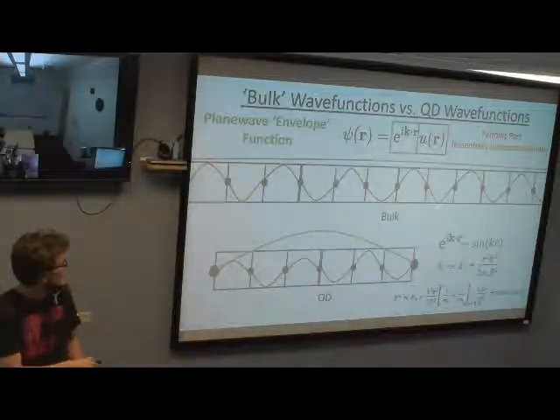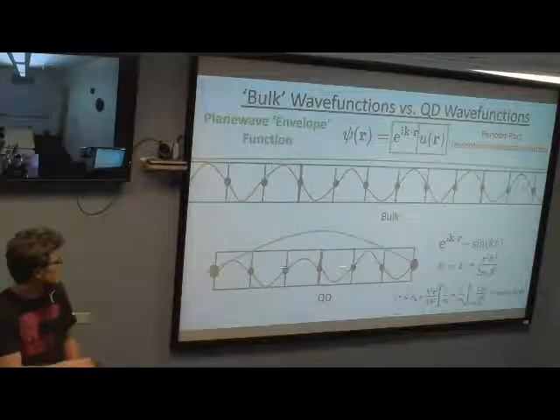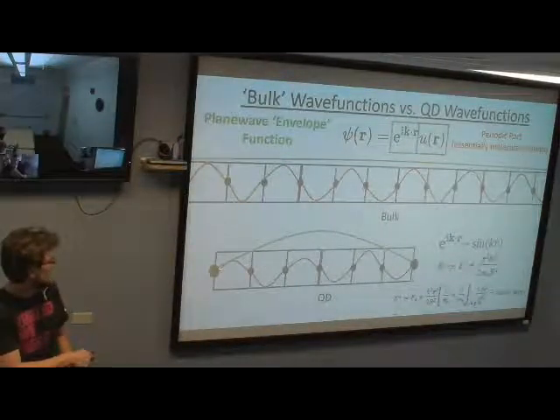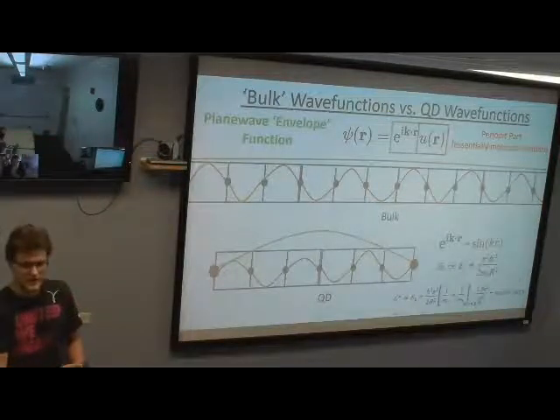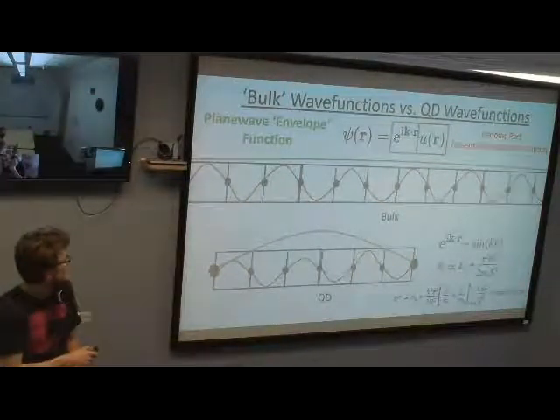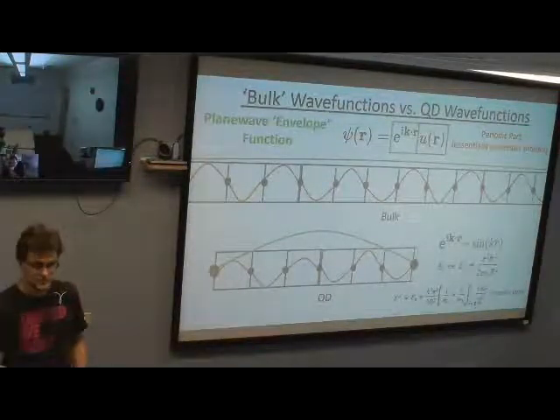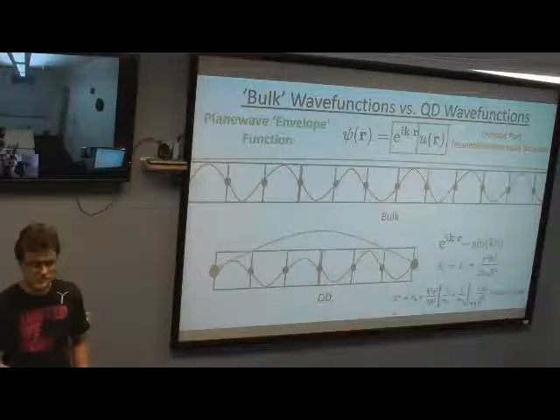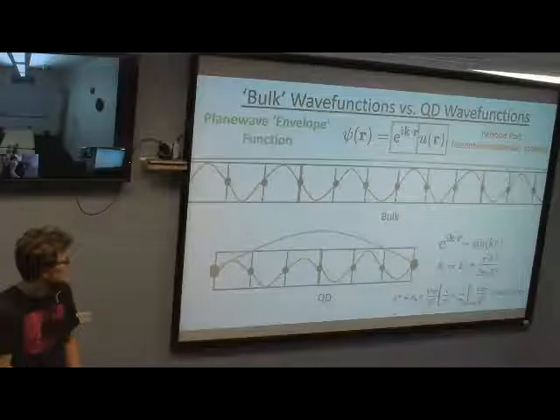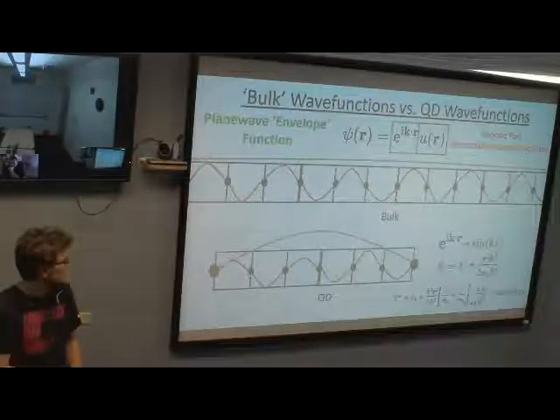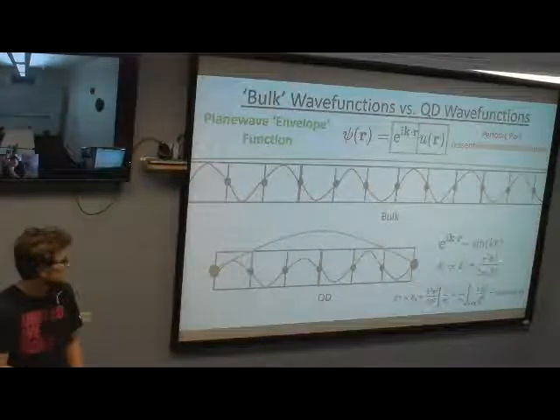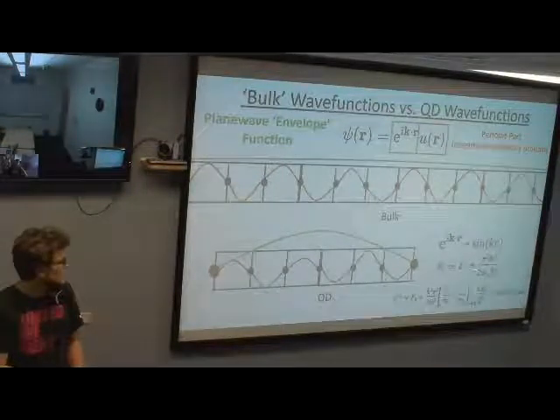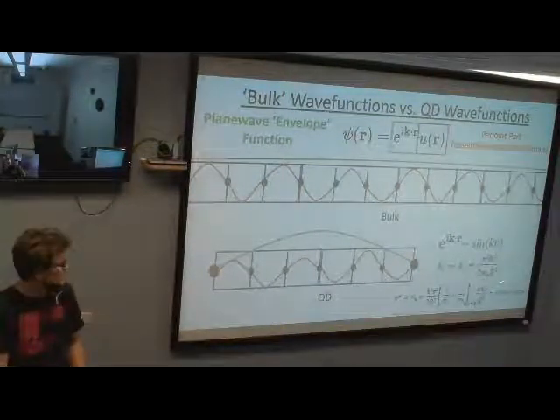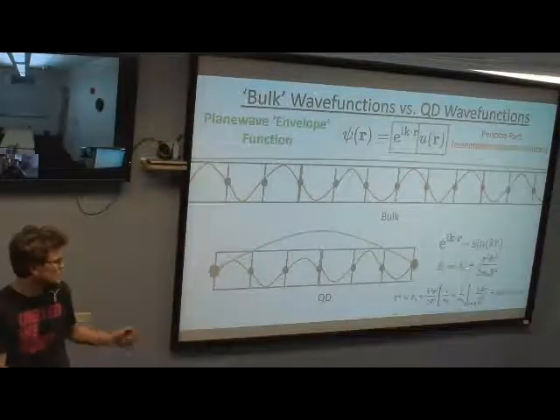And then he realized that if you take a cluster, a finite system, your envelope function basically turns into your particle in a box solutions. So this phase factor turns into a sine wave. And then you do your normal particle in a box solutions that a lot of us have probably done a couple of times. And you arrive at the energy of your state being basically its ground state energy plus some confinement effects. This is what you'd normally see from a particle in a box solution, except he did it for a sphere, so instead of an edge length, he used R.